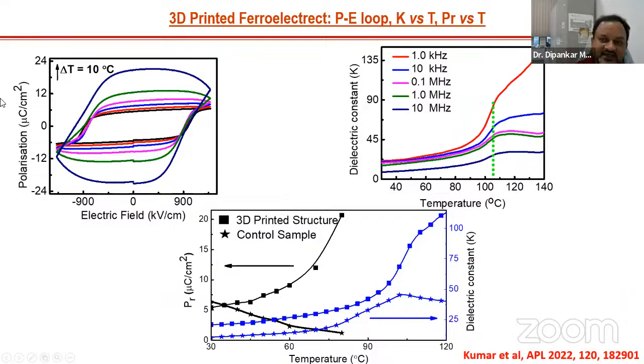Okay. Similarly, in the case of ferroelectricity, what happens? Change the temperature, for example, in this group, then what happens? The remnant polarization basically decreases. But here, remnant polarization increases only because of the electrode structure. So this is the down curve. You see, the remnant polarization is increasing in the case of 3D printed electrode structure.